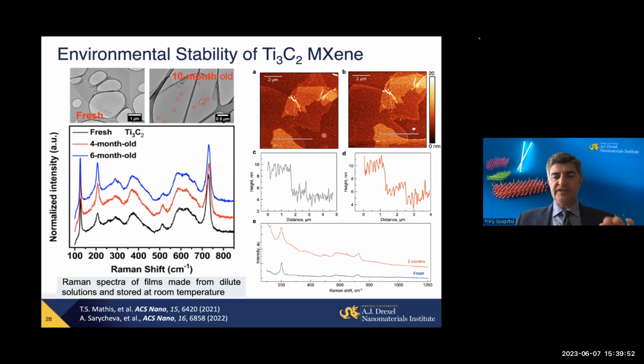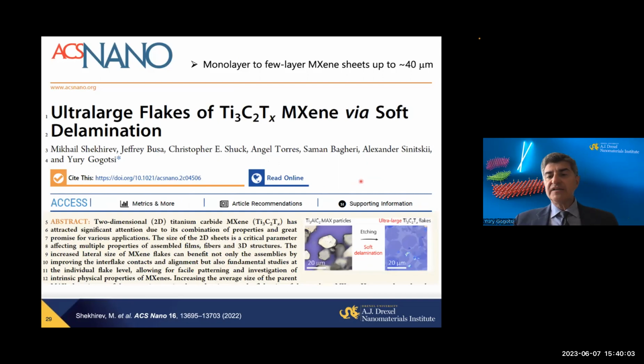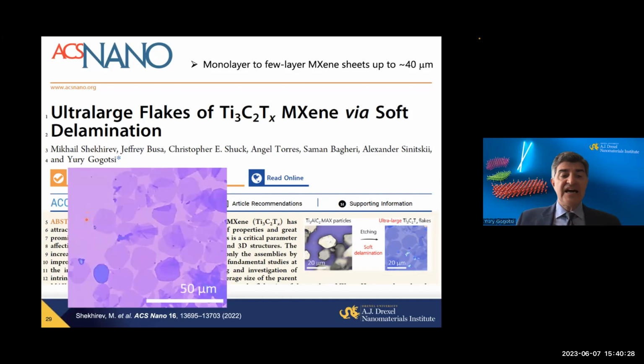So what is important? They are stable. They can be used in the environment. It's very important for many practical applications. We can make large flakes, with sizes actually up to 40 micrometers. You can make graphene with this size. But I've never seen Ti3C2 or molybdenum disulfide or other chalcogenide or oxide or other 2D materials produced by solution processing with this size, because of mechanical properties. MXenes are stronger than any other solution-processed materials, including reduced graphene oxide and graphene oxide.